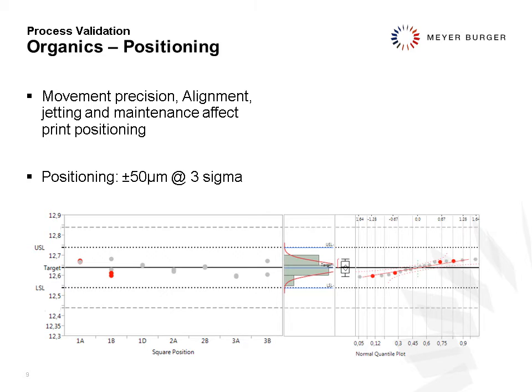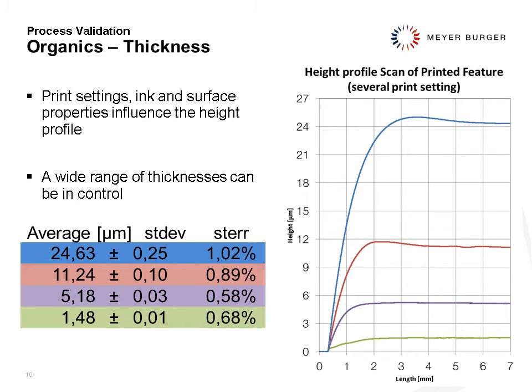If you know that you can position at these levels, you know also that you don't need to take much more space. The design of your encapsulation will actually depend on this number. So the smaller this number is, the less space you need to take on your substrate. Another thing which is important for organics is their thickness. Again, you can influence the thickness by setting the right print setting, choosing the ink and the surface properties, and therefore in the end you will come out with a certain height profile.